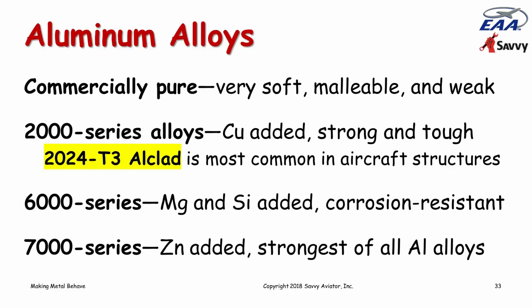The most common is something called 2024 T3 alclad, which I'll talk about in a moment. There's also 6000 series aluminum alloys that have magnesium and silicon added, and those are much more corrosion resistant than other aluminum alloys, because most aluminum alloys are pretty vulnerable to corrosion. The 2000 series ones that we use mostly to build airplanes are quite vulnerable to corrosion. Then there's 7000 series, which has zinc added to it, and it's the strongest of all the aluminum alloys. But of course, being the strongest, it's also pretty brittle. So we're limited as to what applications we can use it in.